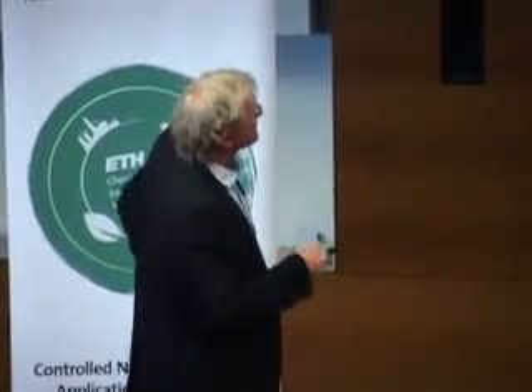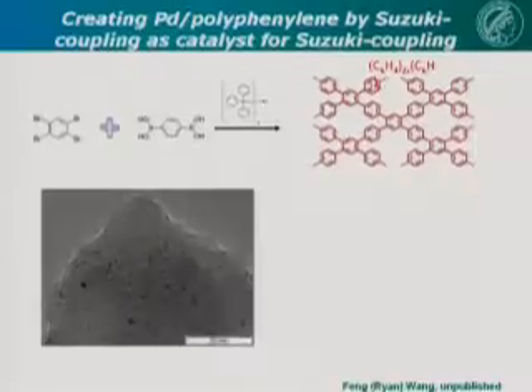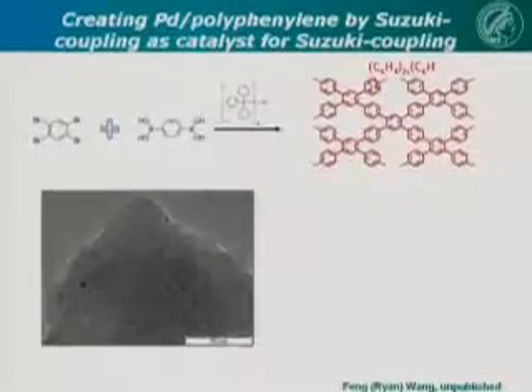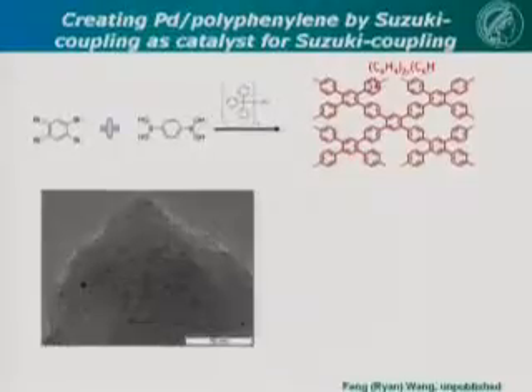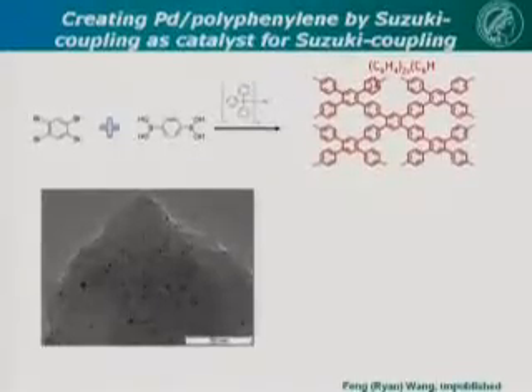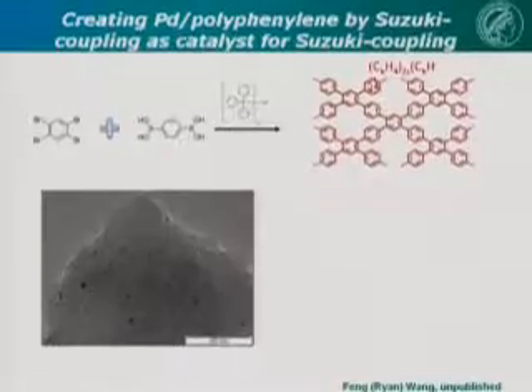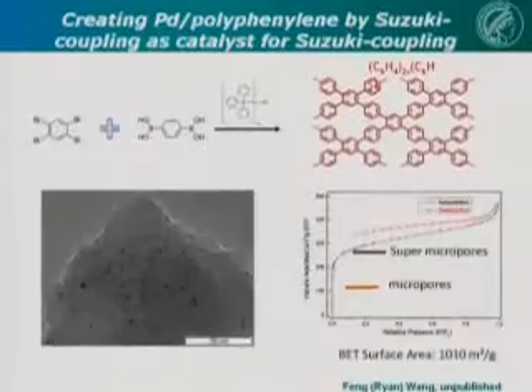The way Ryan did it was he used a Suzuki coupling of these two substrates, the boronic acid and an aromatic bromine compound, catalyzed by palladium to create this polyphenylene. This is a porous, sort of intermediate between graphene and carbon nanotubes, so to say. It's a porous carbon material with very high surface area. And in the process of producing this catalyst, the catalyst for the Suzuki coupling to create the catalyst is actually converted to metal particles which are embedded in the pore system of the polyphenylene. It is very porous.